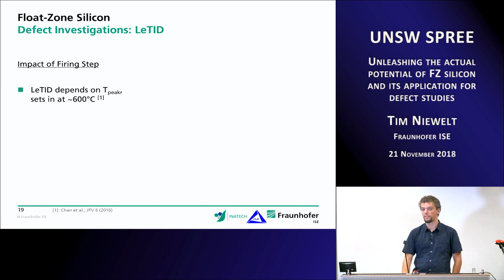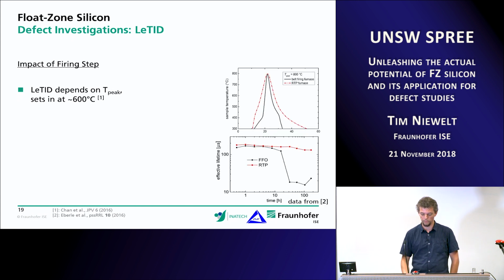Okay, the impact of the firing step. In a solar cell, the firing step would be for contact formation. In this case, we're just simulating that because we know that it's important for solar cells. So we take the samples and subject them to similar temperature profiles. So for multicrystalline silicon, it has been shown in the past that the degradation strongly depends on the peak temperature and usually sets in at a peak temperature of 600 degrees C. So when the samples are fired colder, then they don't degrade. This is one of the results that we have had on this. So we see a comparison of 2 firing profiles.